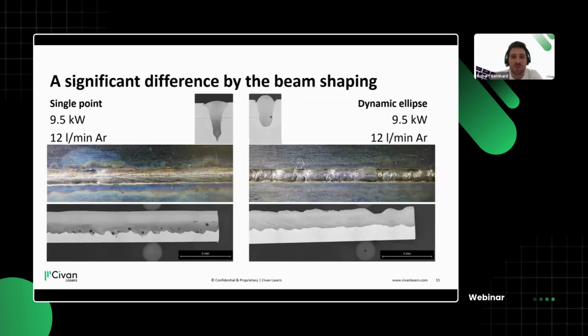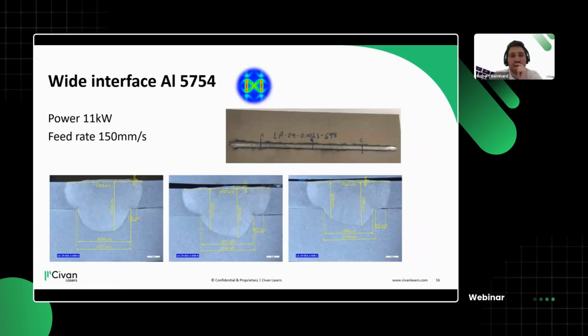What I mean by this: by using a single dot, we have, of course, deeper penetration. This is something we understand. But at the same time, we get a lot of imperfections. And looking at the cross section here, at these high speeds, we are still experiencing some fume issues, but there are no cracks. It's without any inclusions. So we are really happy that we can achieve these high speeds by doing this laser welding. You can even see it here, I think better on the other aluminium, where we can achieve also at a little lower feed rate, but getting very wide weld seams. So dynamic beam shaping here as well helps us to get the weld seam tailored to our needs.